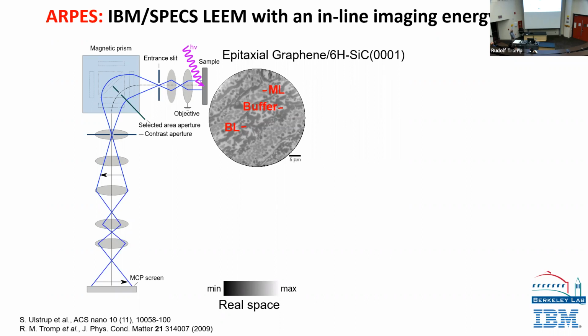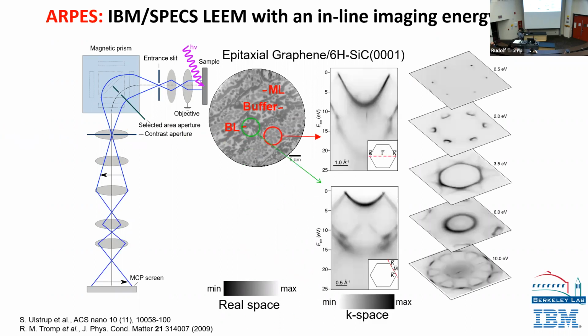You see different contrast here because you may have 1 or 2 or 3 layers of graphene on different parts of the sample, which give different image intensity. So here we have mostly bilayer graphene. Here it's mostly monolayer graphene. We can now map energy versus momentum of the electron, how far they are away from the optical axis, right? In the back focal plane.